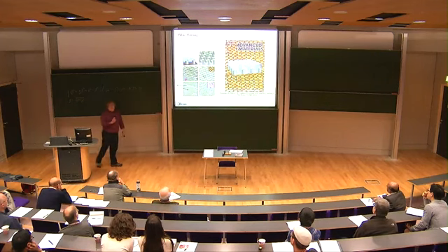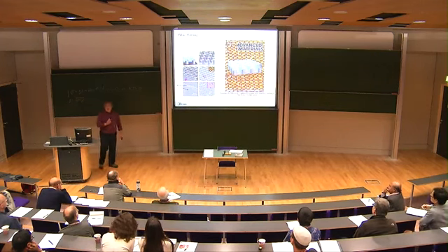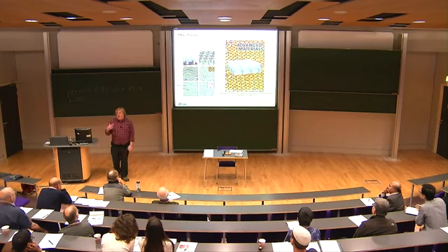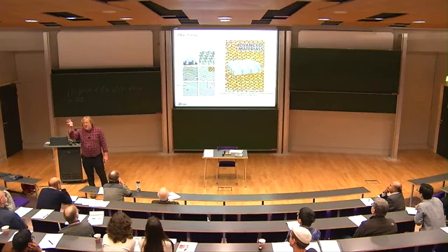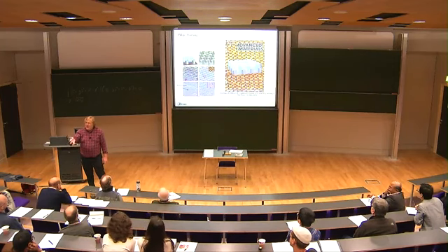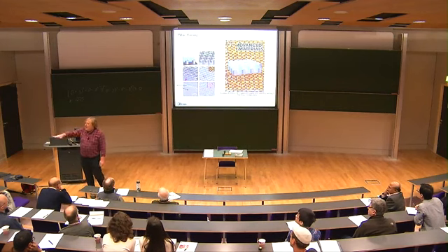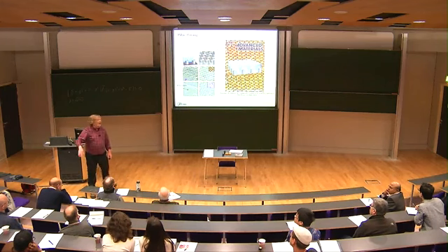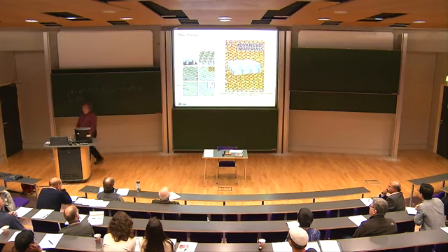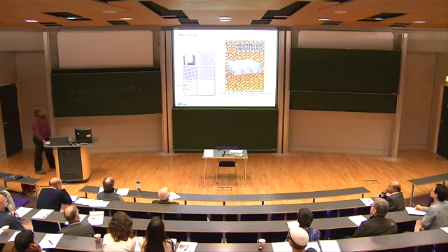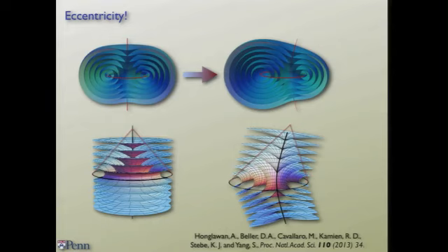Okay? What to me is especially interesting is that you can make 10 micron posts, and as far as we know, as far as we've gone, you can actually fill it up to 40 microns, and you still get the pattern on the top. It's like the princess and the pea. Do they tell that story? Right? You can still feel the posts. You have all these blankets and all these mattresses, right? All these layers, right? And the layers can distort and do all those things, but you can still feel the posts underneath.